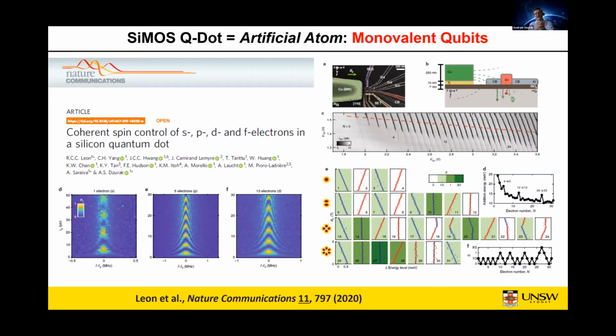Now, if, however, we operate our quantum dots at higher electron densities, this can screen out the effect of materials-related disorder and make our qubits much more robust. So, without going into too much detail, what this paper shows is magnetospectroscopy of each of the electrons added into this quantum dot, all the way from 1 electron up to well above 30 electrons. And as we add an electron in, we find that the energy required to add it falls away because the capacitance of the dot is increasing. But we find that the energy has these jumps when we add the 5th electron, the 13th electron, and the 25th electron. And this is because our quantum dot is acting like a two-dimensional atom.